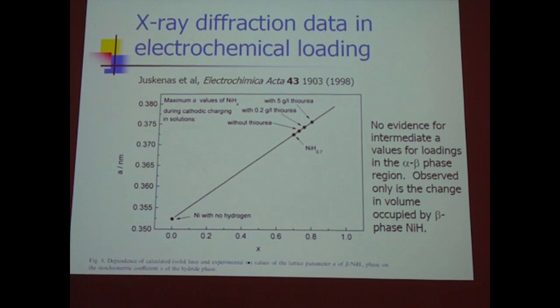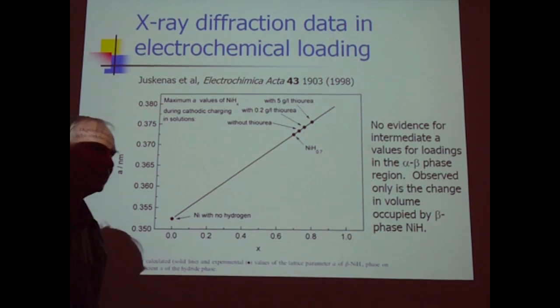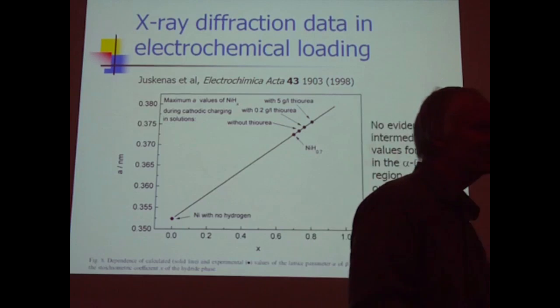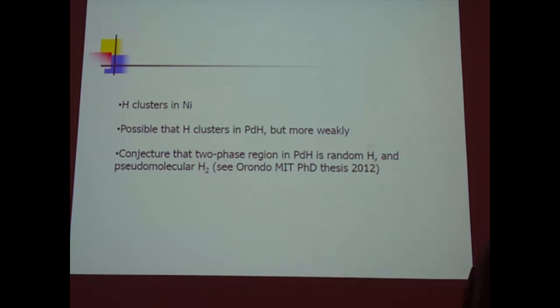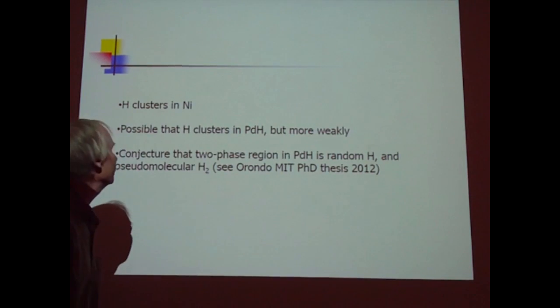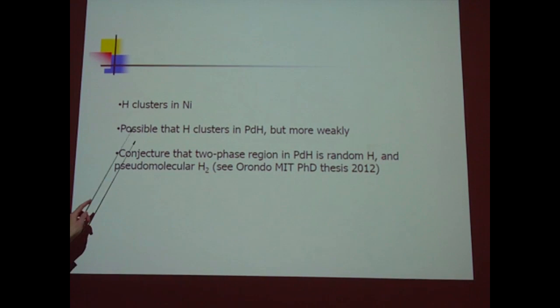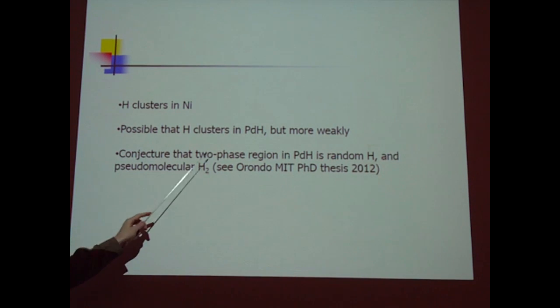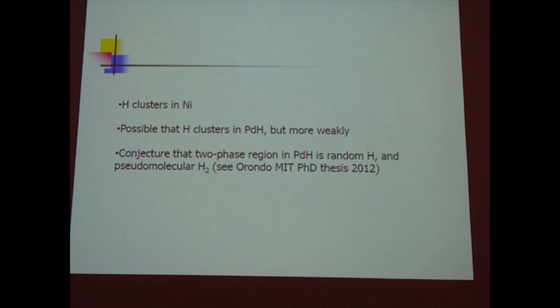This is qualitatively different than how things work in palladium hydride. I submit this is important, and it's cool. So hydrogen clusters in nickel. We thought that hydrogen probably clusters in palladium hydride, but it's a weaker effect. For example, there's a conjecture that you can understand quantitatively the two-phase region immiscibility gap in palladium hydride by saying your two phases, one is random hydrogen, the other is hydrogen pseudomolecules. First example of clumping.